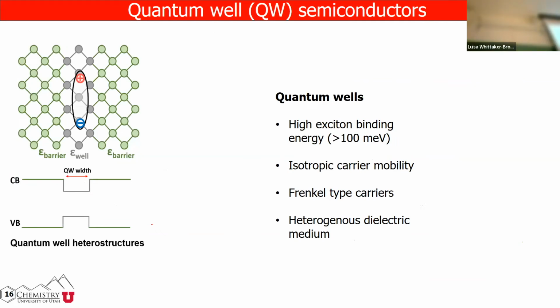Then basically you have these wells where your electrons and holes are confined. And again, the best thing they have going for each other is to recombine. So they form these very stable excitons, where the exciton binding energy is about 100 milli-electron volts. They have isotropic carrier mobilities. Frenkel-type carriers are basically driven by excitonic properties, so that's what Frenkel-type carrier means.